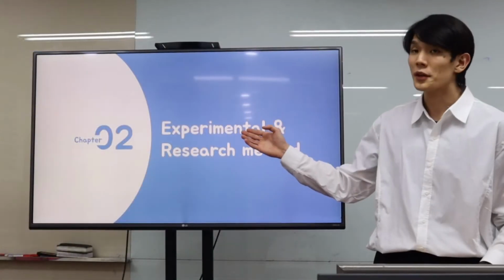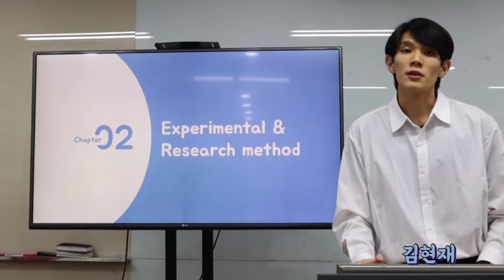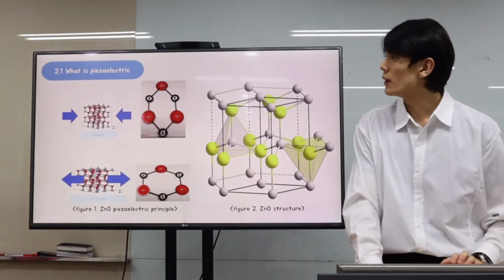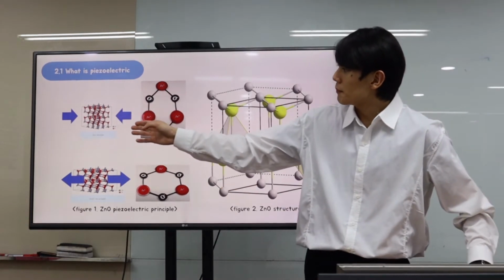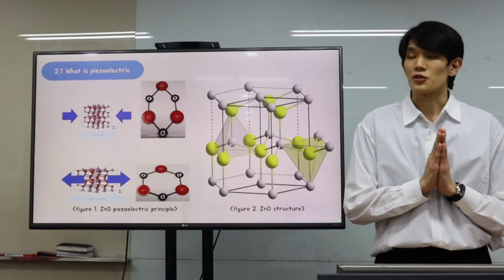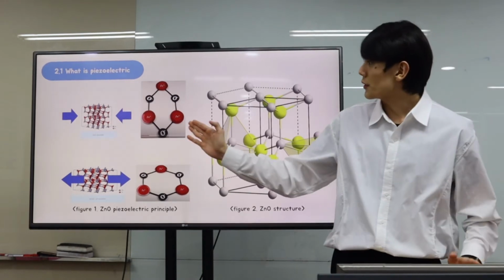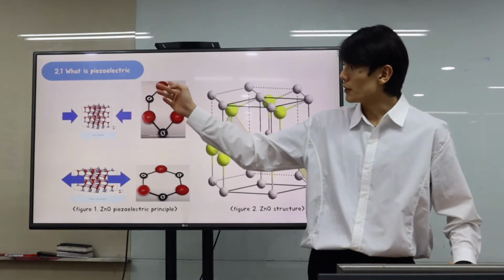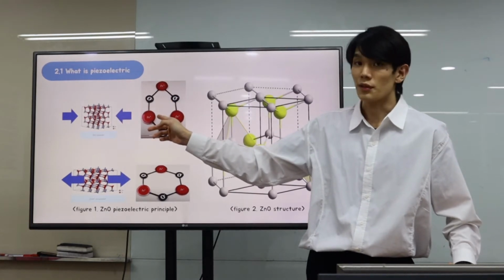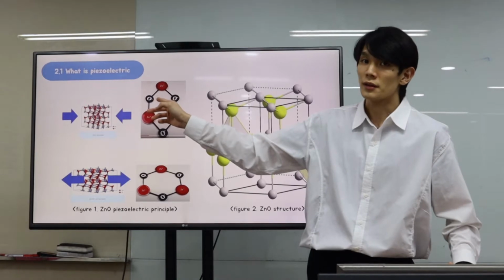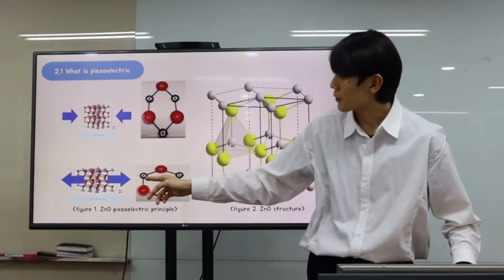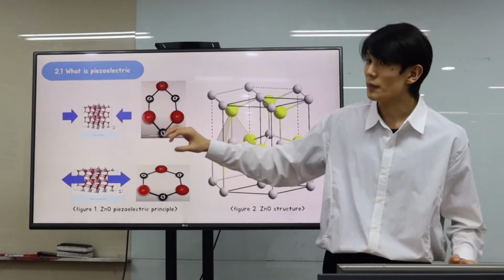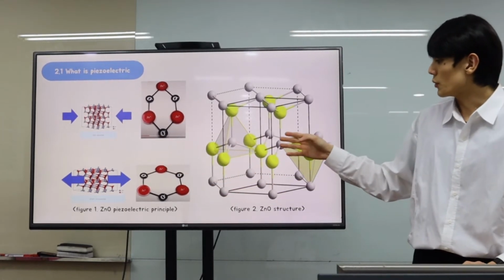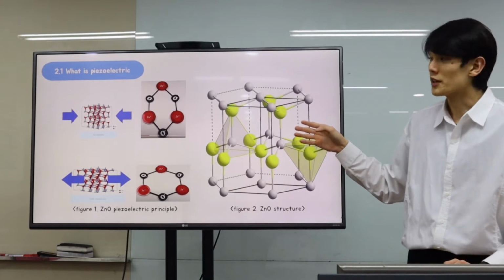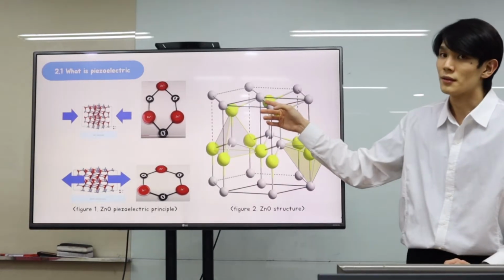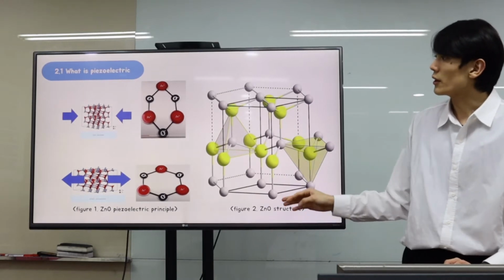So chapter 2, experimental and research method. Now I'm going to talk about why we chose this material. As you can see in this picture, to make a voltage, we need pressure. When we push left and right, the red dot goes down and the black dot goes up. The red dot makes a positive voltage, plus, and the black dot makes a negative voltage, minus. However, when you pull left and right, it makes the opposite voltage. In figure 2, the zinc oxide structure is wurtzite. The center axis is not in the right center, so it can make a piezo effect.